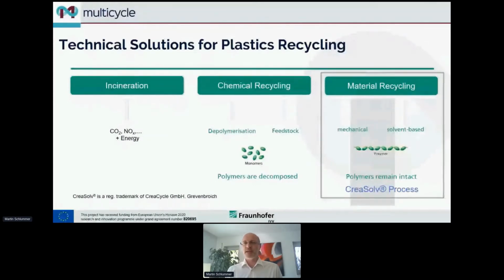Both have in common that they keep all the time at the polymer level. So there is no degradation down to monomers. And this is important since we, of course, want to have an economic and an ecologically sound processing. Ecologically sound is a bit critical for chemical recycling, since all the energy which has been put in polyamide and polypropylene earlier is destroyed in this step here. And it means after all the long way back to the monomers, we have to reapply the same amount of energy to come back to the polymers. So this is something where we have just theoretically very high CO2 emission or CO2 footprint in our backpacks.